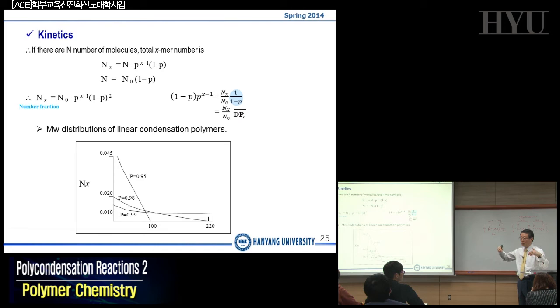So X is plotted on the x-axis, and y here is Nx. Because we have 3 variables in one equation, Nx, X, and P, we can just iterate the known equation with a known variable, where we assume that P is equal to something. If P is equal to 0.95 here, and you calculate X versus Nx, then you come up with this line here.